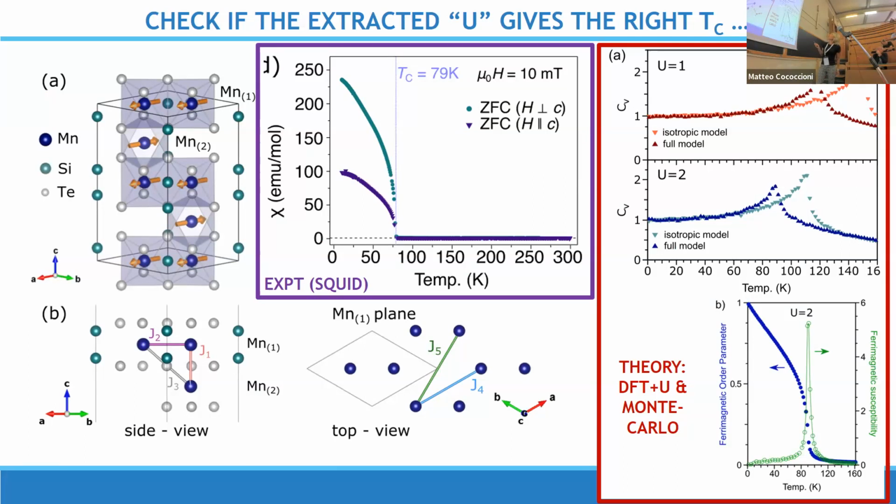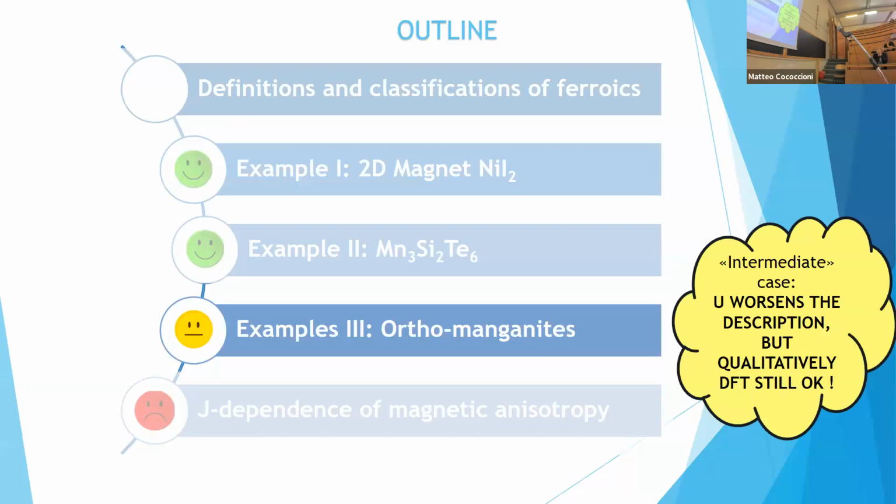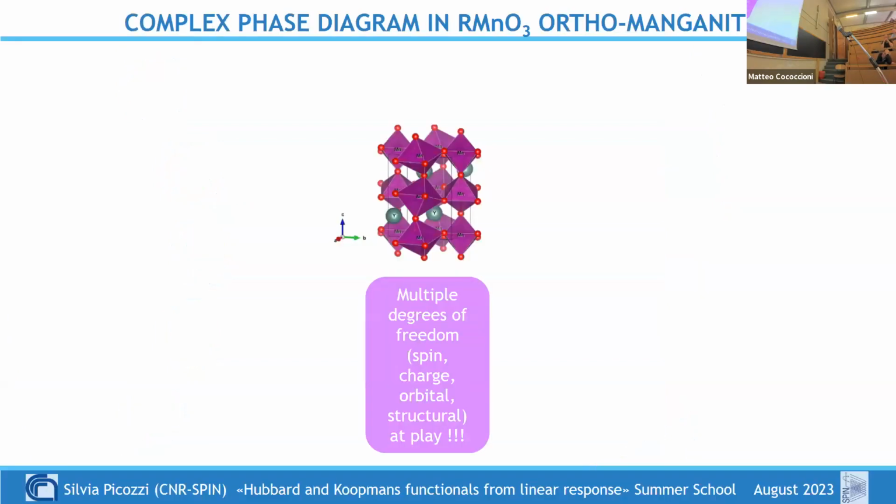You see that the Curie temperature is something around, I don't know, 100, and experimentally it is about 80. It's good. We can never expect Monte Carlo and DFT to reproduce exactly the ordering temperature. So we are kind of satisfied here, even here, with the help of experimentalists. Quickly, the description gives the right trend, but of course, not a quantitative description.